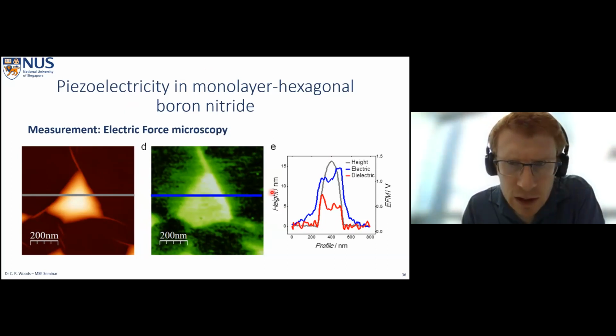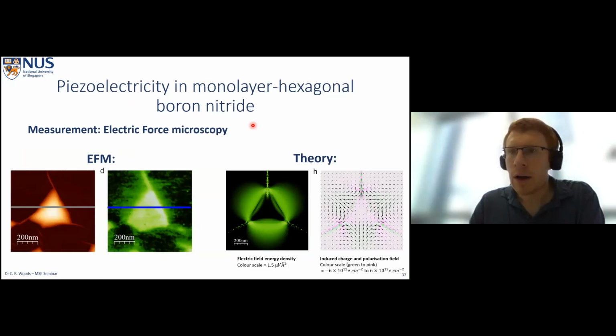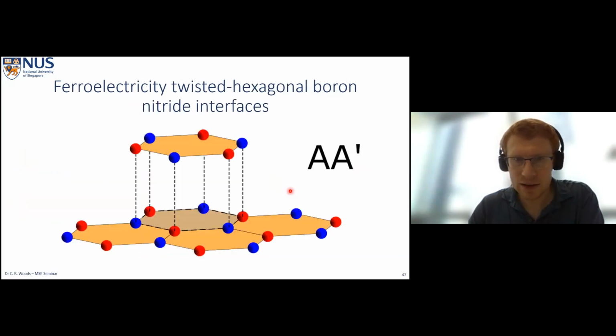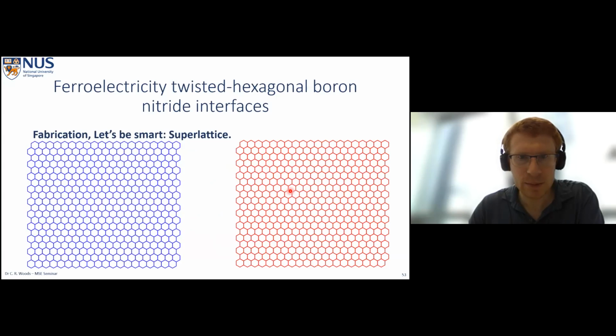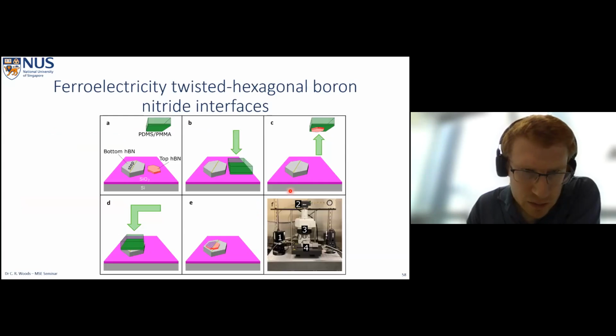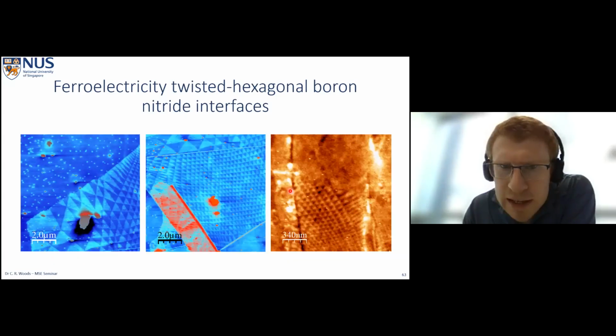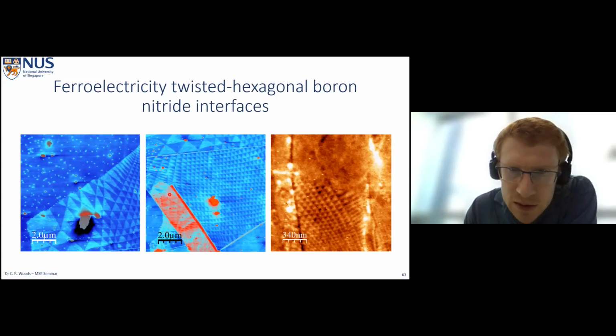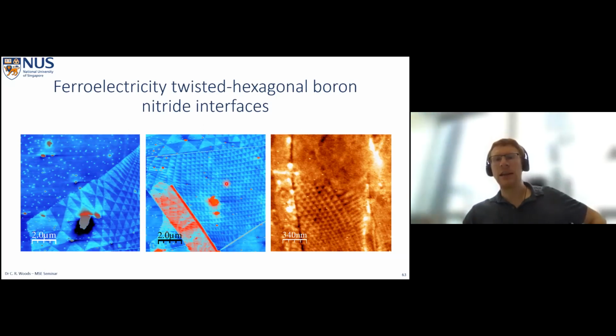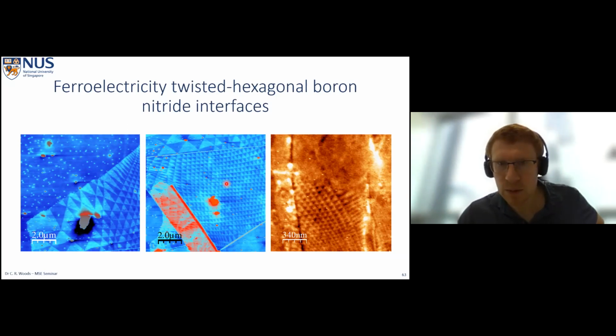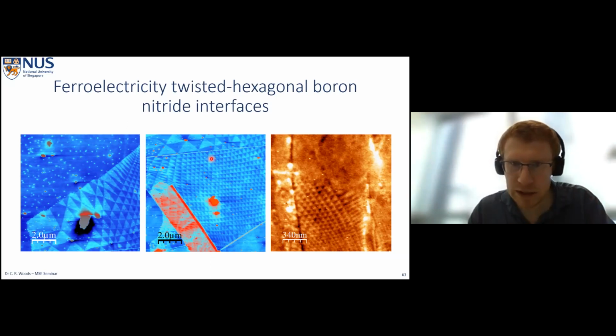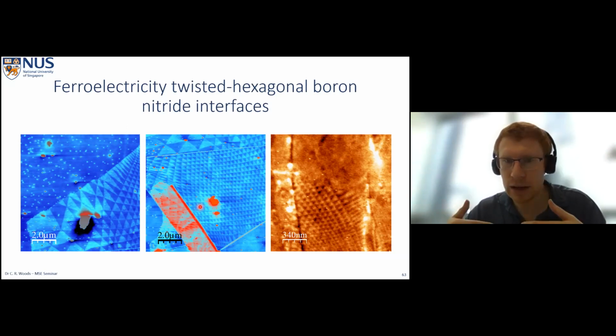The second half of your question, so how does it affect superlattice formation? Then I have to jump forward again. So let's see, we can actually see some contamination in the images here. Here we have a large piece of some contamination. Do we see some bubbles here? No, we don't, but we have contamination on the surface. Maybe something here. I'm not sure exactly what this is, but contamination in this case doesn't affect our overall measurement because the effect is so strong that we're not worried too much about contamination. If there is any contamination between the layers here, we can expect that it would be ironed out into these big bubbles that we see in the first half of the talk.